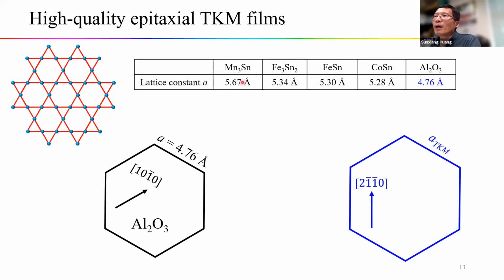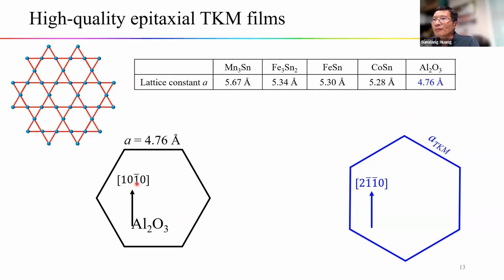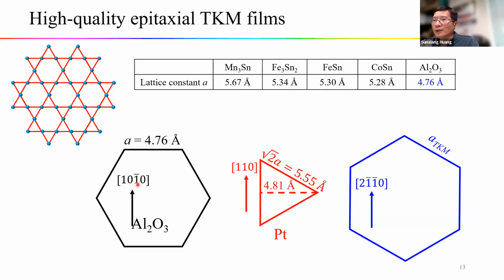So for those binary compounds, they have hexagonal structures with a lattice constant a of more than 5 angstroms. The lattice constant of a common hexagonal substrate, aluminum oxide, is 4.76 angstroms, which is more than 10% less than those values. However, if we rotate this aluminum oxide (001) by 30 degrees, we can actually get a good lattice match between the aluminum oxide and the platinum (111).